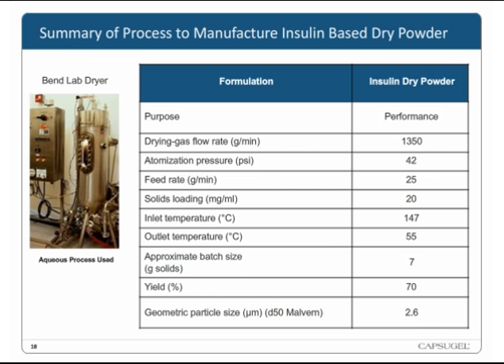And we started with our customized Bend lab dryer, which, as mentioned in a previous slide, spans the scales from about 200 milligrams of powder up to hundreds of grams, depending on how much solid you can dissolve in your spray solution. The purpose here was to make and collect particles around a mass median aerodynamic diameter of 2 to 2.5 with a GSD value on an impaction test of 2 or less. Using all the tools that I mentioned on a previous slide, we mapped out a process space and used that to select these conditions.